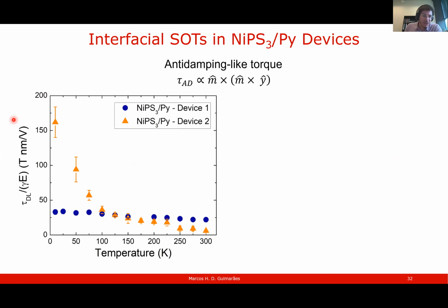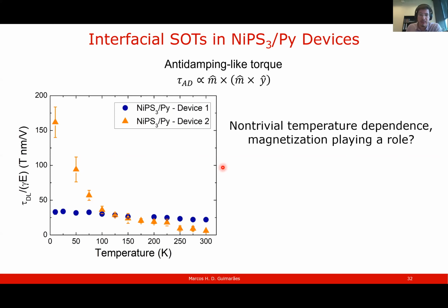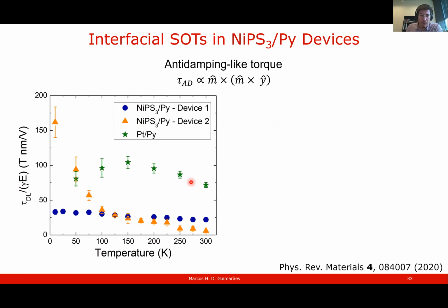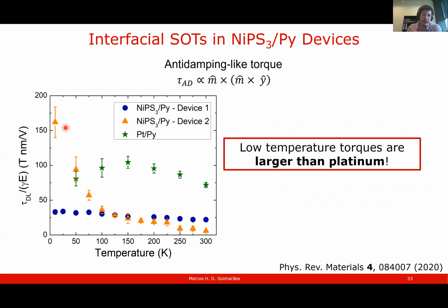Now, very interestingly, the damping-like torque, the M cross Y, which is the spin Hall effect-like torque, depends much more strongly on temperature, but the response is different from device to device. But now if you compare to the standard platinum permalloy, then we have something that at low temperatures is much stronger than platinum. So we have an interfacial torque that is much more efficient than the standard in the field.